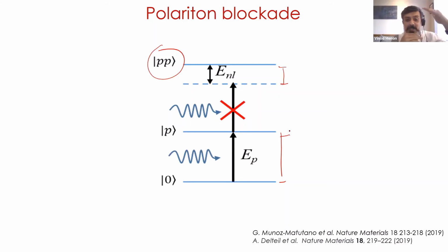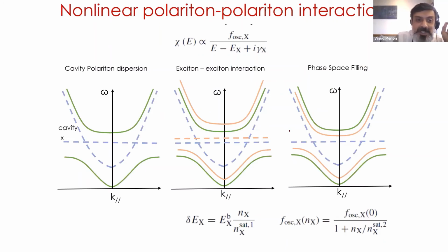And this shift is coming about not because I have increased the number of oscillators, which also happens, but that is different from what I'm talking about here. What is really happening here is I take my cavity photon, I get a polariton state, I introduce more excitons into the system. The exciton-exciton interaction essentially creates a net shift in my exciton energy, and that comes about because of the dipole-dipole interaction. I've renormalized my exciton energy level. I shifted it up, and because of that, now I have shifted all the energy levels up. So if I sit here and I watch what happens, I see that if I increase my exciton density, it has moved up, and this is what I was telling you about the shifting in the previous slide.